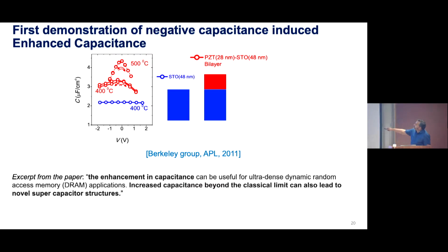But we were able to show that you have a dielectric and you put a ferroelectric on top. So you have increased the thickness. Convention will say that capacitance should go down, but here the capacitance went up even by 2x. And later on, in many experiments, we were able to show that you can get 4x, 5x increase in capacitance. Again, very unconventional. And although we have mostly focused on looking at transistors, at that time, this is an excerpt from the conclusion of the paper: the enhancement in capacitance in this way can help other applications like DRAM and like supercapacitors.